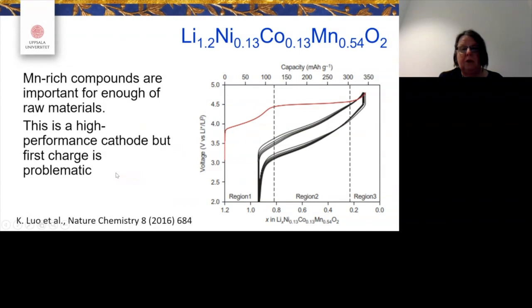My last example that I will just browse quickly, I tend to like to talk about batteries, so I speak far too long, is a study we did which also shows that you need to work with many characterization techniques at the same time. And again, this is a manganese-rich one, and it's lithium-rich, and it has a huge capacity compared to the other one. But you see, you lose a lot of it during the first cycle. So what's really happening here before it gets nice? It means that this is very detrimental if you want to build a battery on this, because you lose a lot of the capacity already in the first charge.